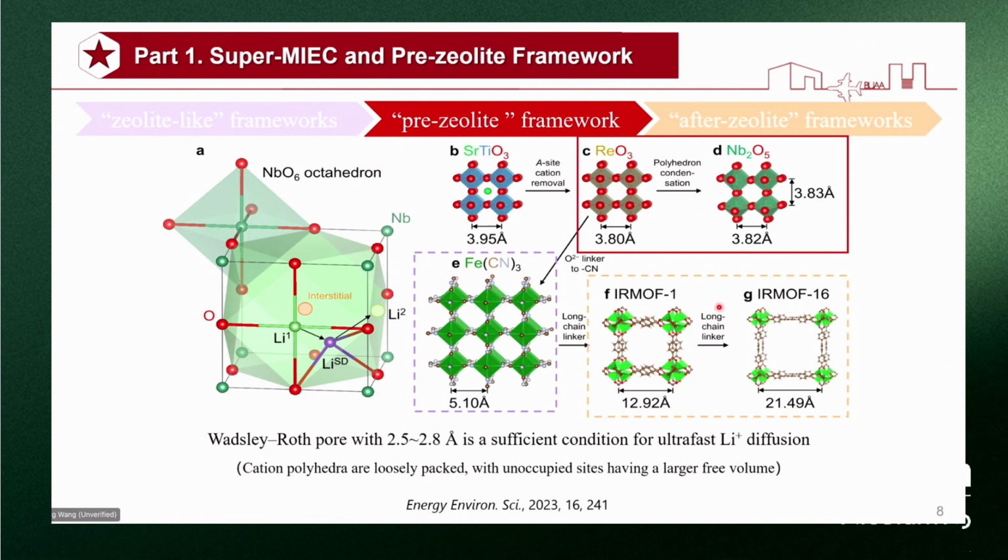These open frameworks often tolerate a wide variety of molecules inside the pores, and surface diffusion allows rapid mass transport for materials that can fit inside the pores. Some Prussian blues and MOFs are even electronically conductive, making them super-MIEC conductors. But these large-pore open frameworks will not store too many alkali metal atoms, and thus are not optimal for high volumetric energy density for charging electrodes.